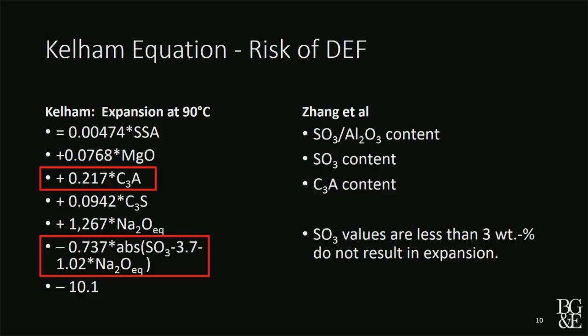There have been other people develop equations. Zhang developed another equation where he looked at sulfate aluminate content ratios and the C3A contents. But overall, the research has shown that sulfates less than 3% don't result in expansion. And I think that's what we're seeing fairly consistently, that the cement chemistry and the sulfate content is a critical factor.